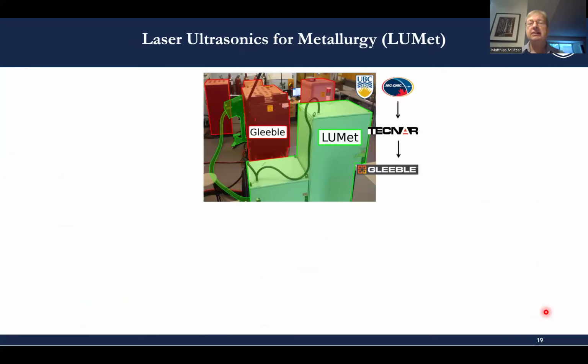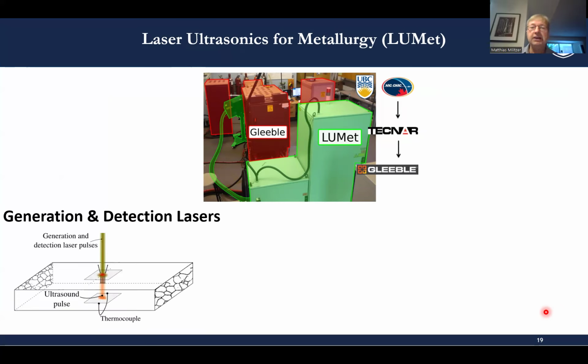Okay, now I would like to use a couple of minutes to talk about another technique that can be used to make austenite grain size measurements. That's laser ultrasonics for metallurgy, or for short LUMET, that we have in our laboratory as an attachment to a Gleeble thermomechanical simulator. What is basically happening here is we have two lasers, a generation laser that ablates the surface of the specimen and creates a broad ultrasound pulse wave that travels through the specimen, and the outcoming wave is detected by a second laser.